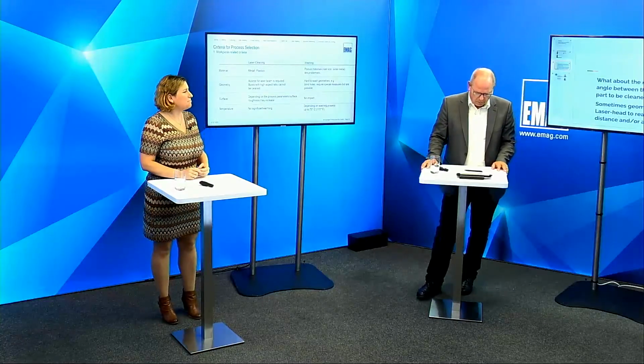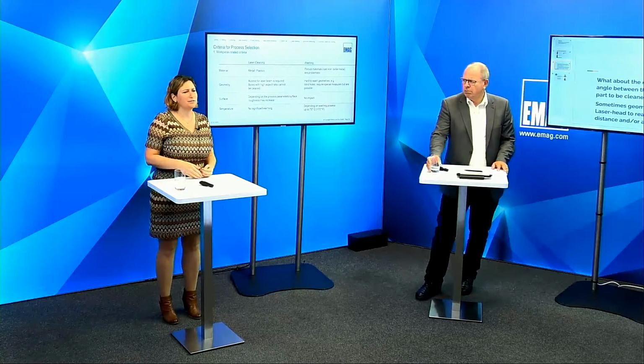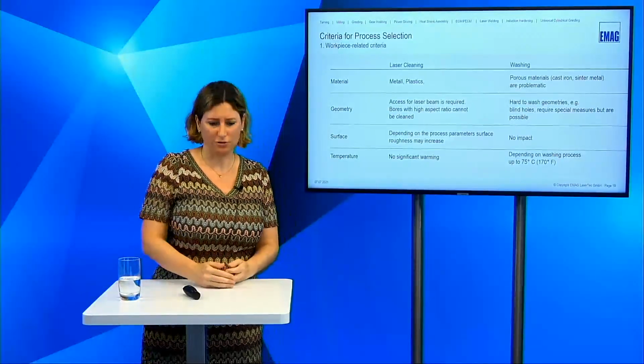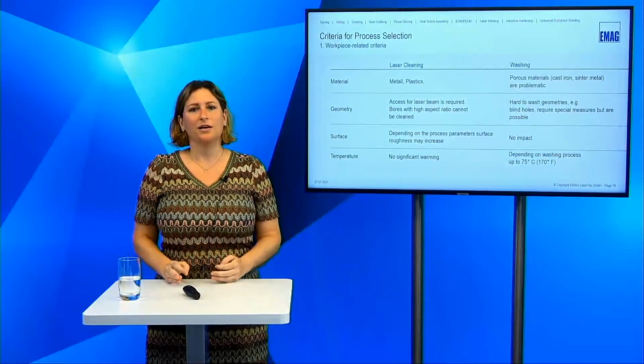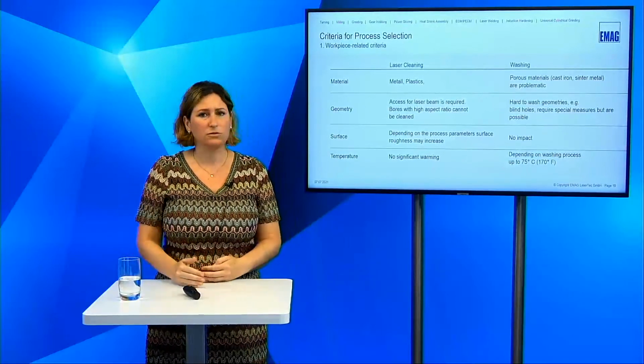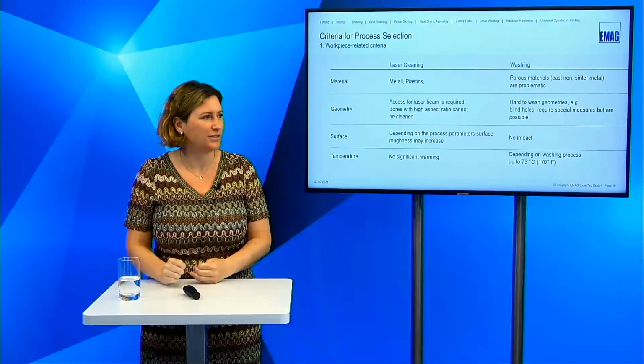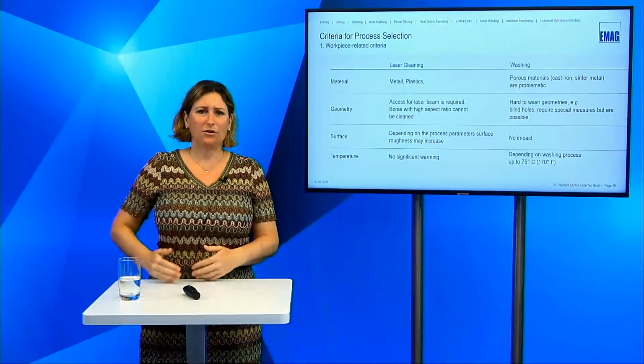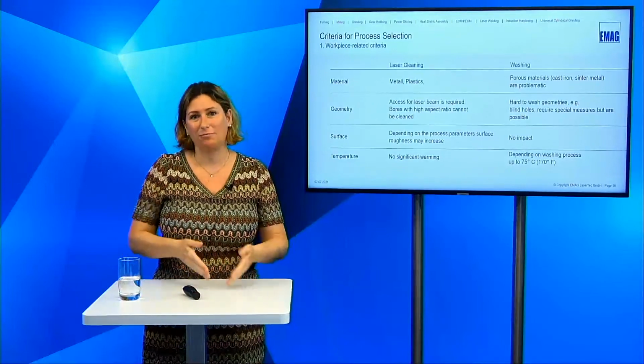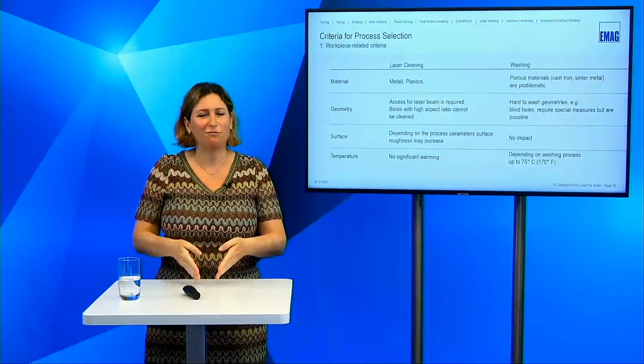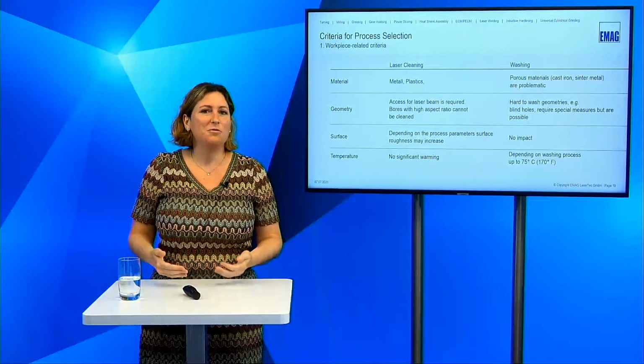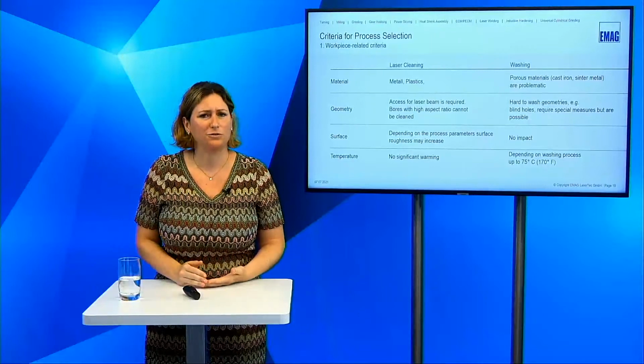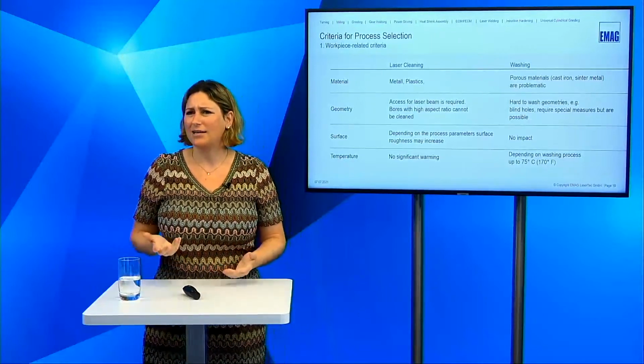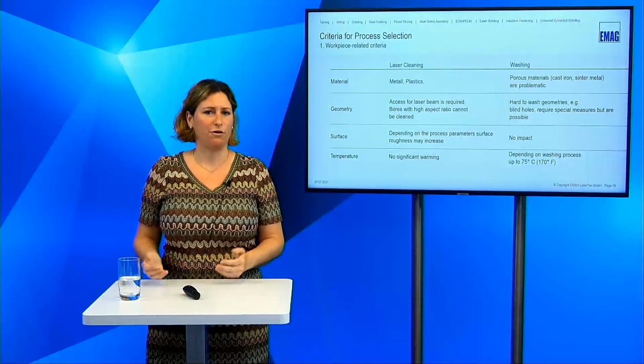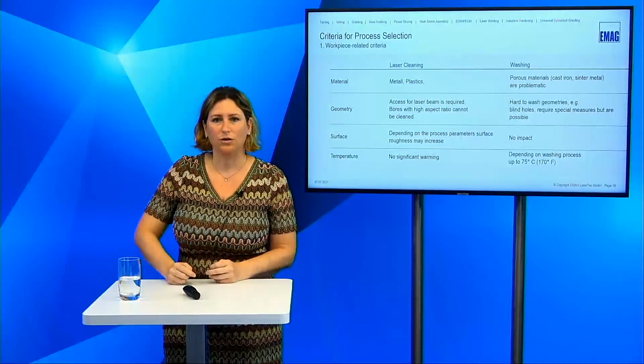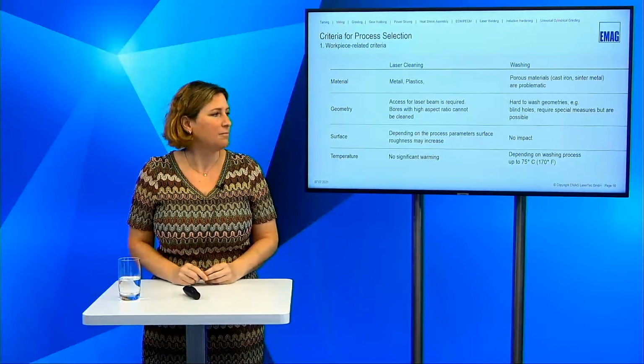So regarding the min-max distance, this depends on your scan system and your objective. This defines at least the distance. So you can have a look on this and choose especially one for this. The angle is also, the laser beam must be absorbed by the surface. So you need to take into account the minimum angle that will be absorbed at least by the surface. So for metals, it's I think about 20 degrees which you need minimum so that the laser beam will be absorbed by the surface.